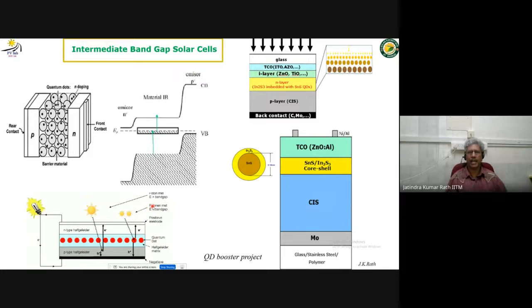The other one is called the intermediate band gap solar cell. That means you take one material with a certain band gap, and light with energy smaller than this normally passes through. But what you do is you put another material which has a band gap smaller than half of this one, so that you make an intermediate band here. You can excite the electron from here to here and from here to here again. So this way you can utilize this low energy light which was normally lost. One of the ways to make this is, let's say, tin sulfide with an indium sulfide shell. As you told, it has to be a quantum dot, because that's a single state, and no band here. So this is one of the ways we try to do.